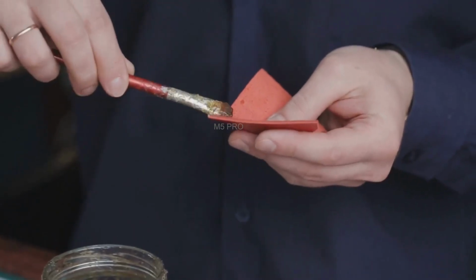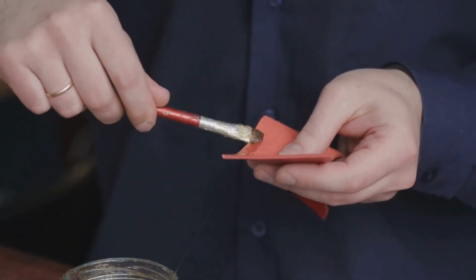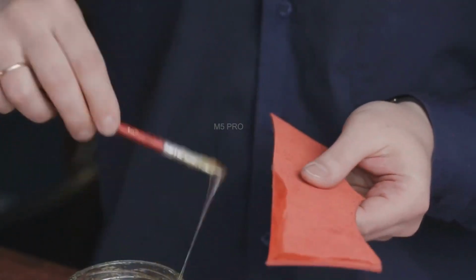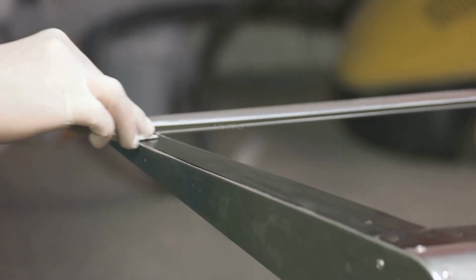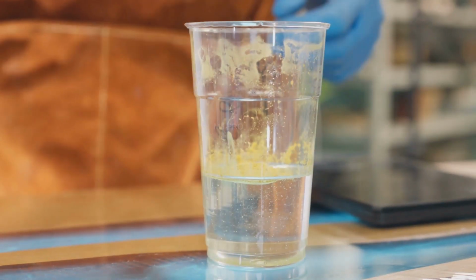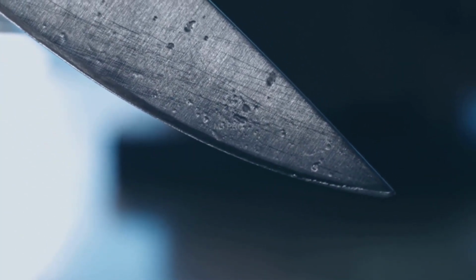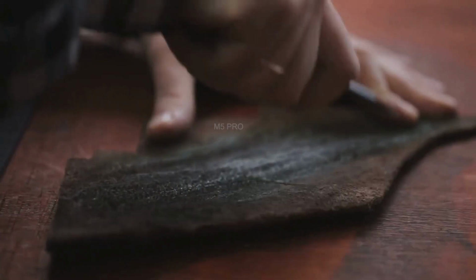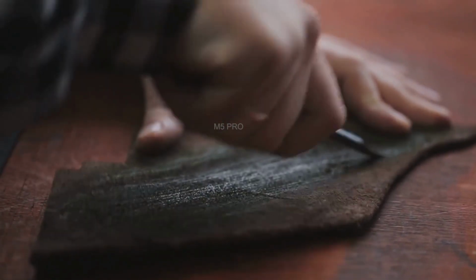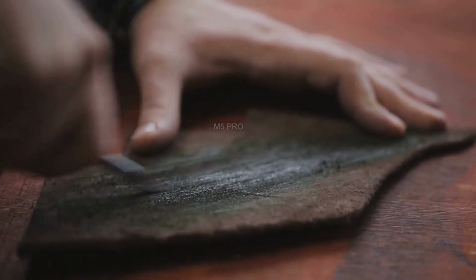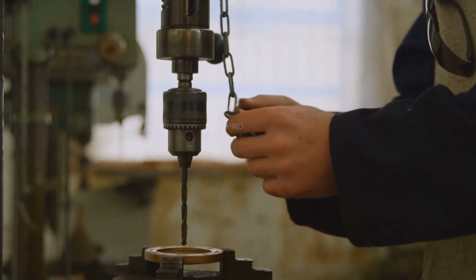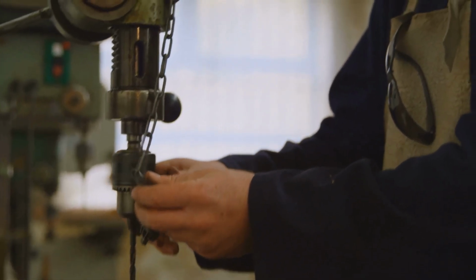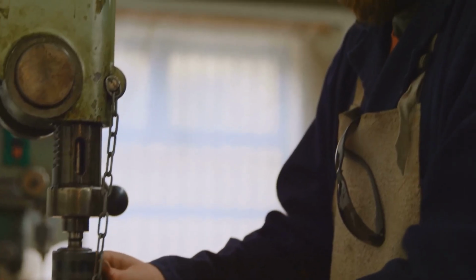A thin, even layer of high-strength, waterproof epoxy is applied to the inside of each handle scale and to both sides of the steel tang. This epoxy serves two purposes. It creates a powerful, permanent bond and completely seals the gap between the steel and the handle material, preventing any moisture from getting inside. The two epoxy-coated scales are then carefully placed on either side of the tang, sandwiching the steel. The operator makes sure the pre-drilled holes in the scales line up perfectly with the holes in the tang.